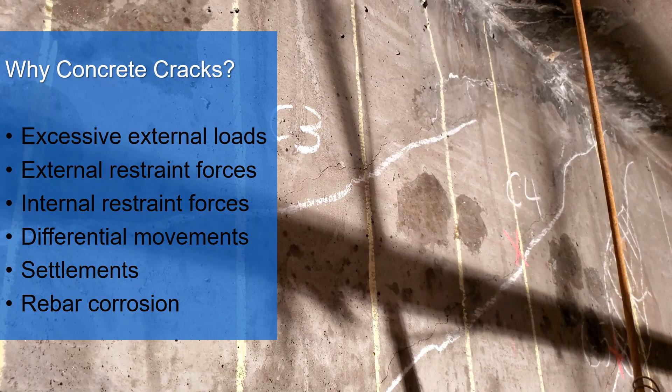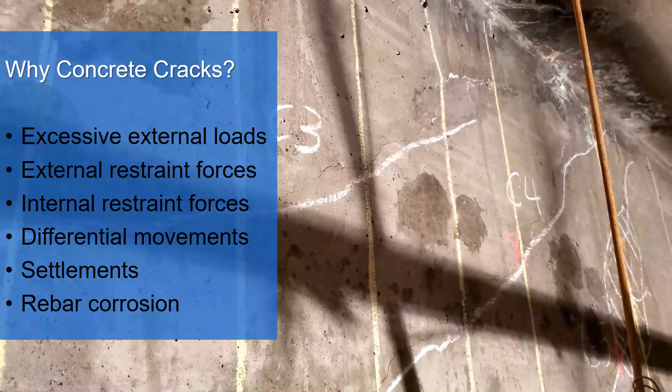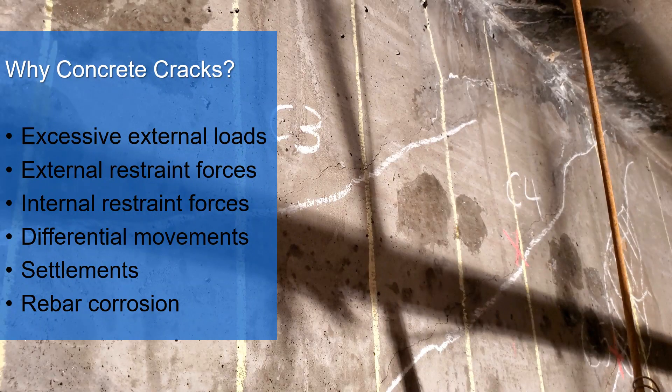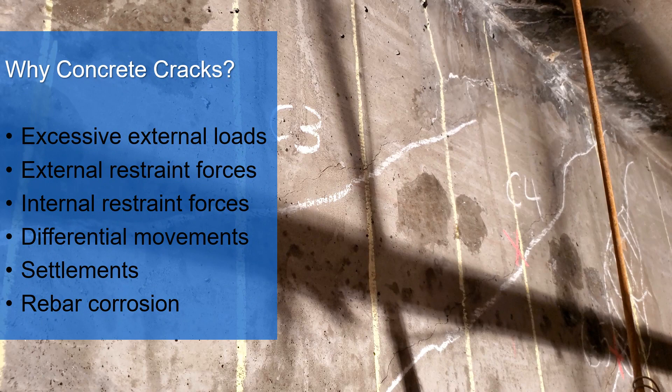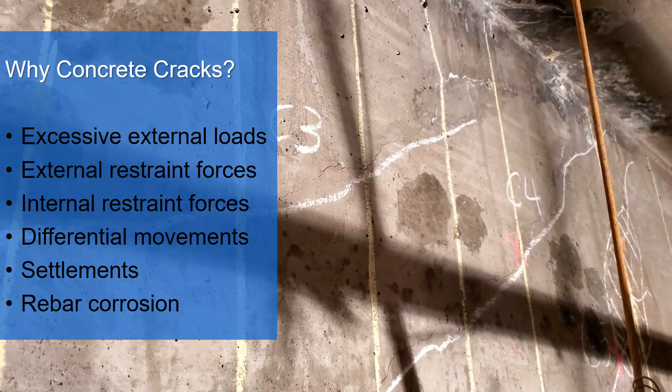In a concrete beam, tensile stresses are initially carried by the concrete and reinforcement. When the tensile stress in the beam exceeds the tensile capacity, the concrete cracks. After this point, the tensile force is transferred completely to the steel reinforcement.